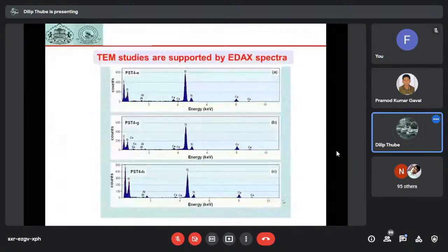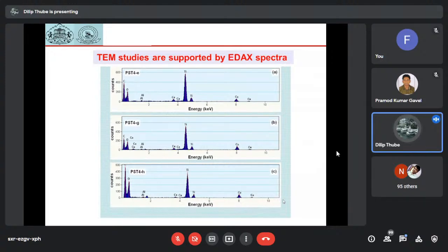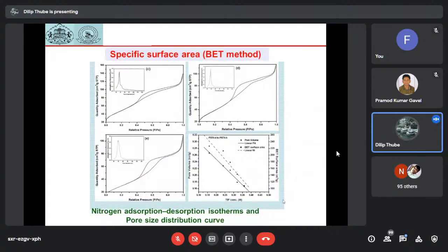Yeah, it is that. So these are EDAX studies of the materials, and they clearly indicate the presence of titanium as well as calcium and aluminum, which means the materials of our desire have been synthesized. Surface properties have been measured by using the BET method, by using nitrogen adsorption and desorption method.